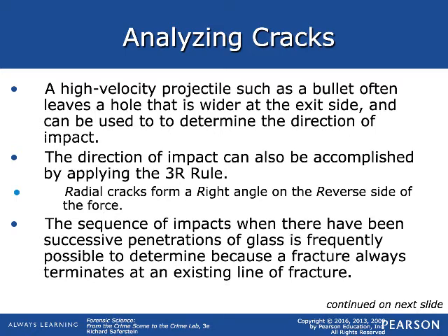So, the sequence of impacts when there have been successive penetrations of the glass. If the glass is being hit over and over again, like maybe it's an automatic weapon and they're shooting it a bunch of times, it's possible to determine the sequence or the order that the impacts occur, because a fracture always terminates at an existing line of fracture.